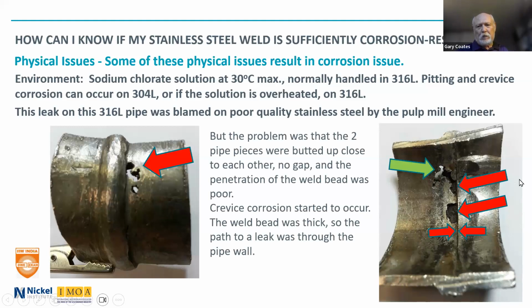The two pieces of pipe were butted up to each other. There was no gap there. The welder put a bead on top of the two pieces of pipe, and the crevice corrosion started. And as I say, that particular environment, sodium chlorate, is known to cause crevice corrosion. However, because the weld bead was so thick, the path to the leak was through the pipe wall.